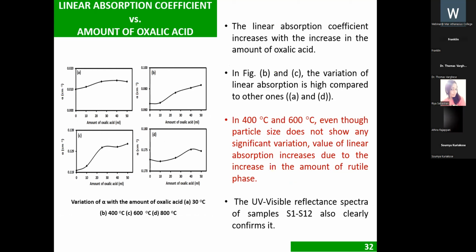It is visible from B and C compared to A and D. But in A and D there is also an enhancement that is mainly due to the increase in particle size, due to the agglomeration which occurred by the presence of oxalic acid here.